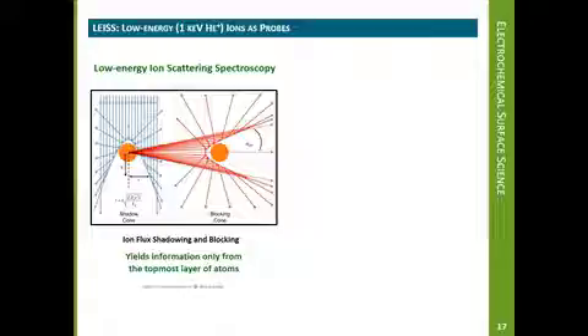One such set of results is the dramatic surface enrichment of a single component in a metal alloy as revealed by the application of low-energy ion scattering spectroscopy. In this technique, inert gas ions are scattered from surface atoms with a scattered energy that is dependent upon the identity of the surface atom. By analyzing the scattered ions, the identity and relative fractions of the topmost atoms present can be deduced. This topmost atom sensitivity is due, in part, to shadowing of subsurface atoms by the topmost atoms.